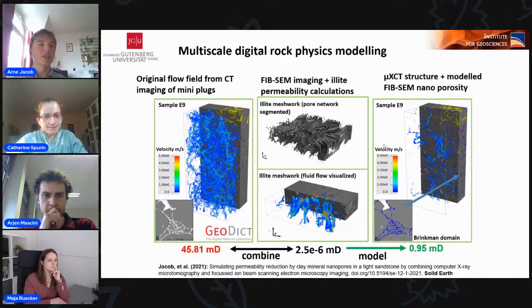We added this information to all of our samples, which were measured by synchrotron tomography, and calculated the permeability of these samples with Brinkmann domains. On this slide, the workflow is shown for an exemplary sample. We can clearly observe, and we also expected that, the overall velocities of the voxels decrease. You can see on the left-hand side, it is very bluish, which means higher velocities than on the right side. This was expected since the permeability of the Brinkmann domains slows down the complete fluid flow through the rock.